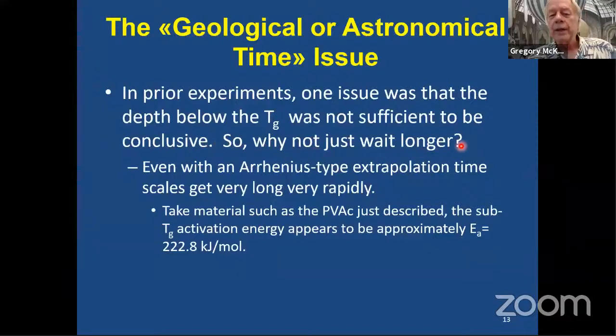Well, so why not just wait longer? Here's a reason. Even if I just assume an Arrhenius type extrapolation for time scales, they get long very rapidly. It's really hard to do the experiment. So I'm going to take a material, PVAc. We've done work on PVAc in addition to other materials, and the sub-Tg activation energy is about 220 kilojoules per mole. This is typical of glassy materials anyway. They have high activation energies below the glass transition.